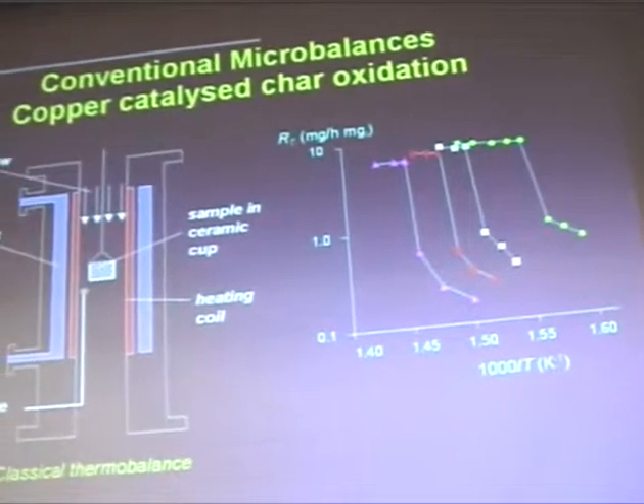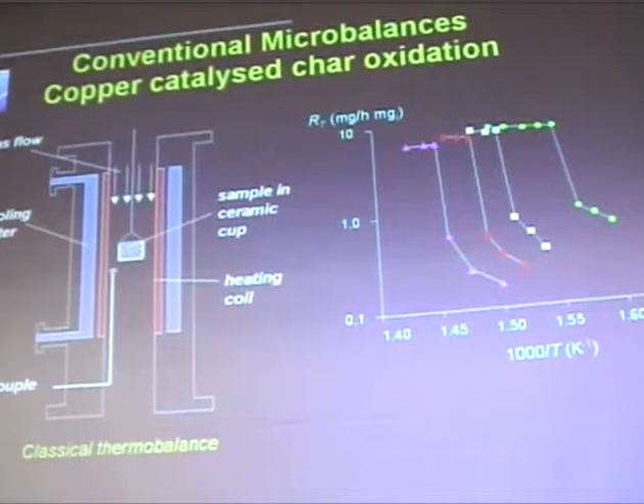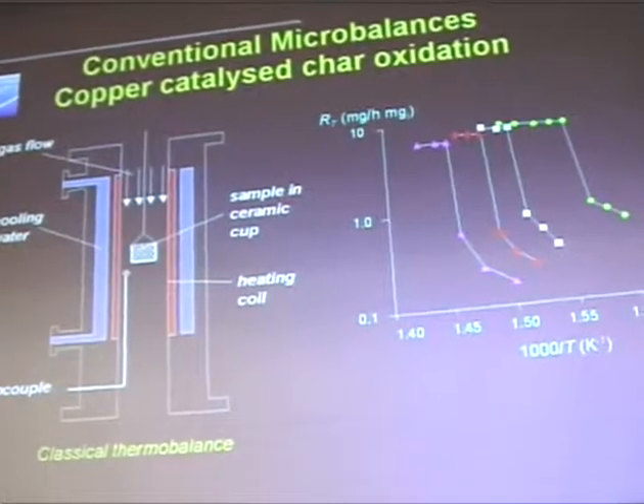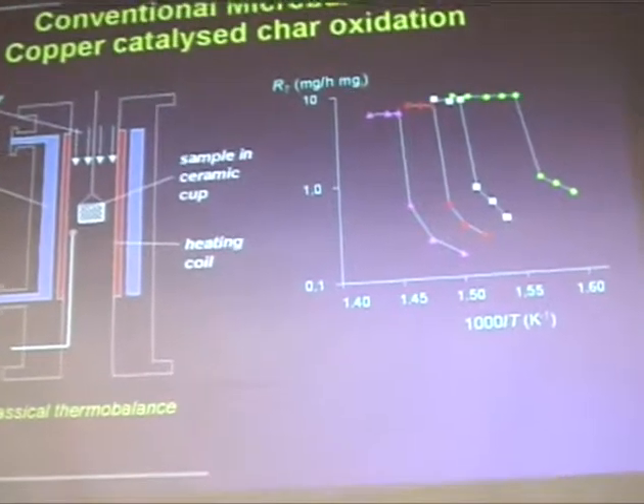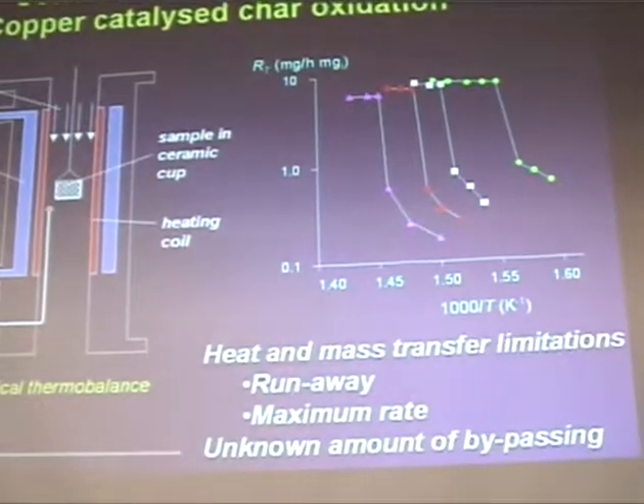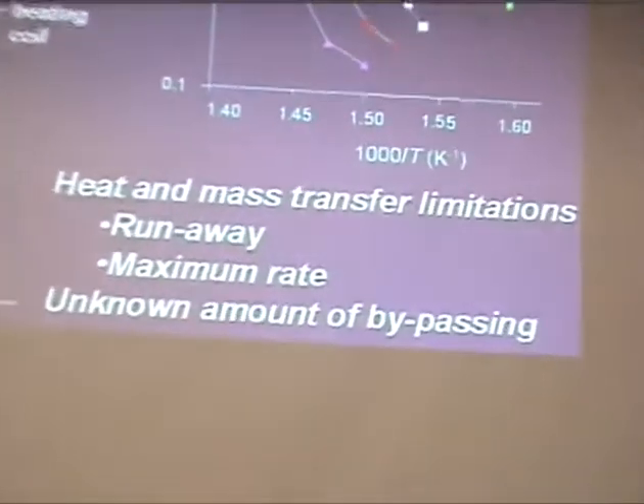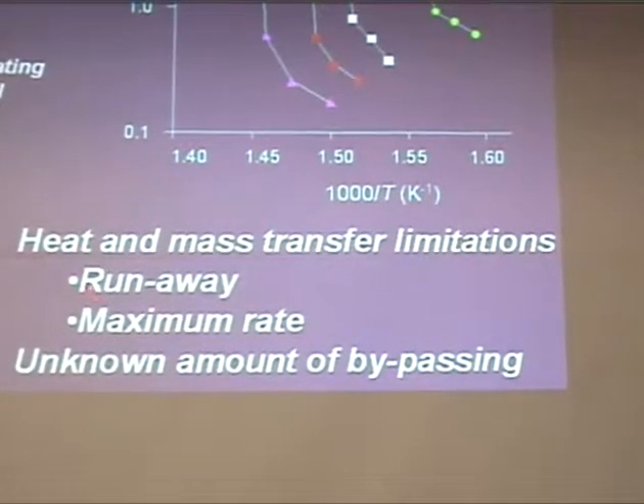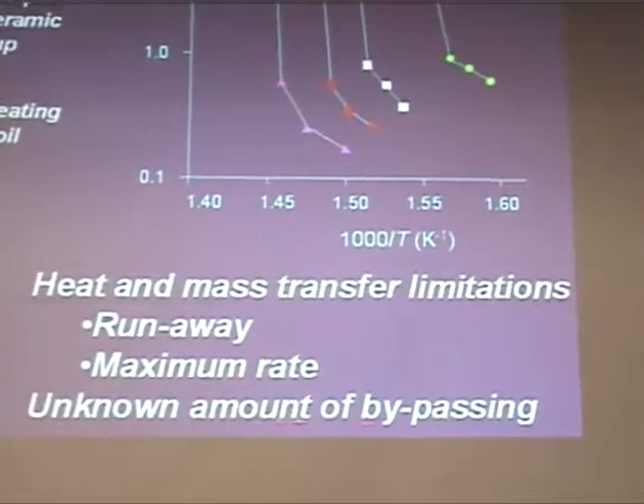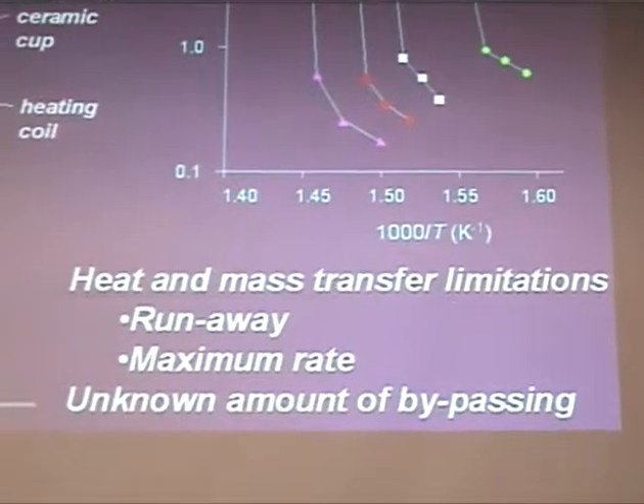And on top of that, you should also see a maximum here, about 10 milligram per hour per milligram. Of course, that's a little bit dependent on the flow rate, but it's also completely externally mass transfer limited. So you could say that the classical microbalance has some limitations: runaway, maximum rate, and also an unknown amount of bypassing.